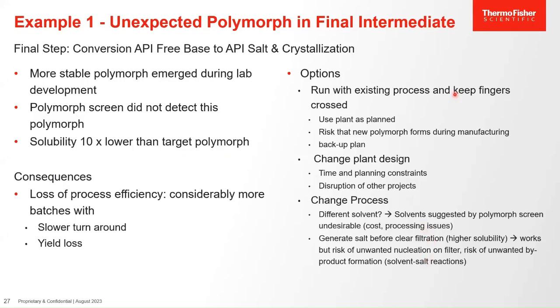Okay, so finally, I'd like to present briefly two case studies. The very first one actually concerns a case where unexpectedly a more stable polymorph emerged during lab development in preparation for a manufacturing campaign. Now, for this particular API, polymorph screen had been carried out and did not detect this more stable polymorph. Unfortunately, the solubility of this polymorph was indeed a factor of 10 lower than the target polymorph.